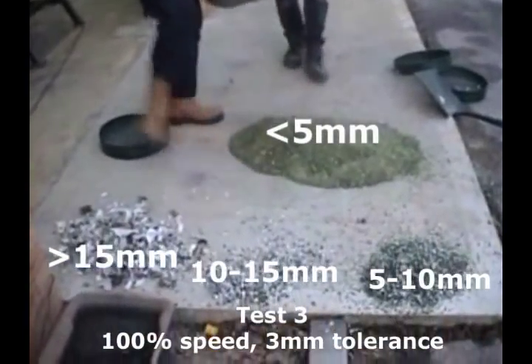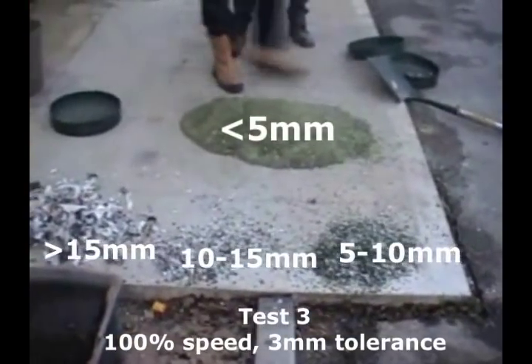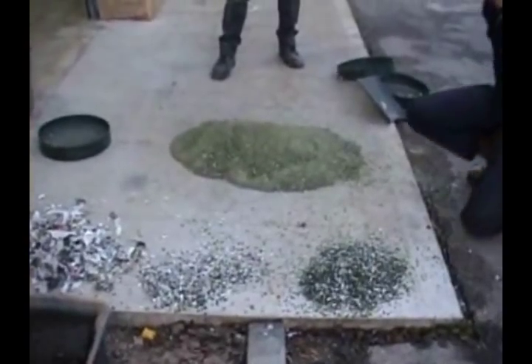You can really see the proportions here. Bearing in mind there's a significant volume of dry waste material, if you were to base this on density, somewhere in the region of 80 to 90% is within the sub-5 millimetre category. We'll pan in to the oversize material, and then to the fine material to have a look at how little paper there is in there.